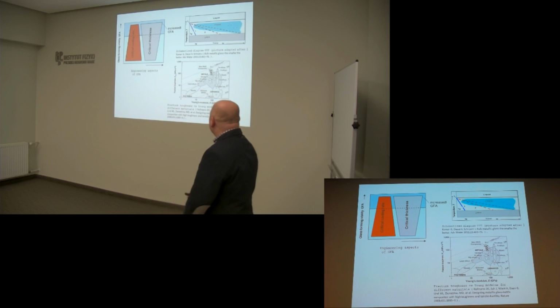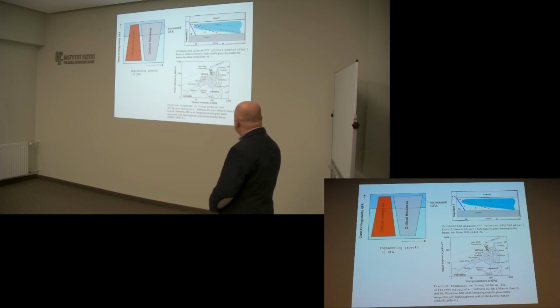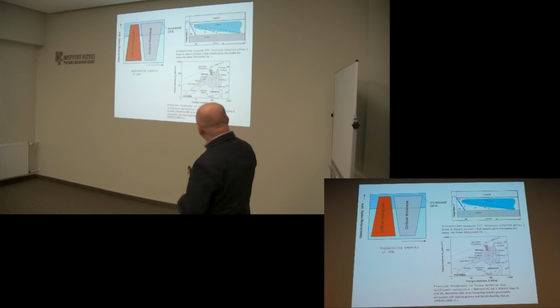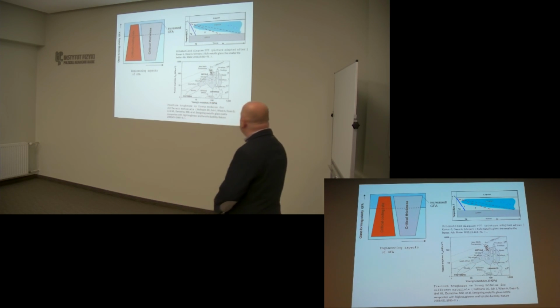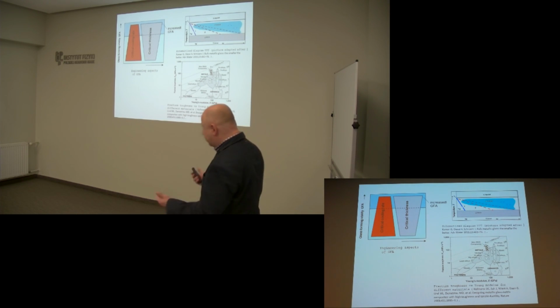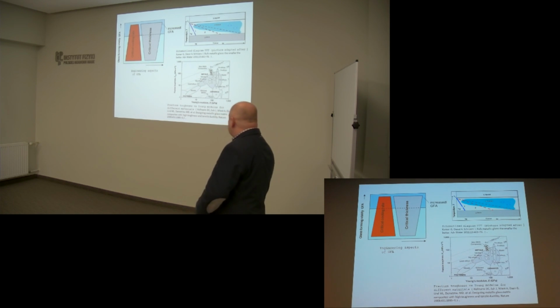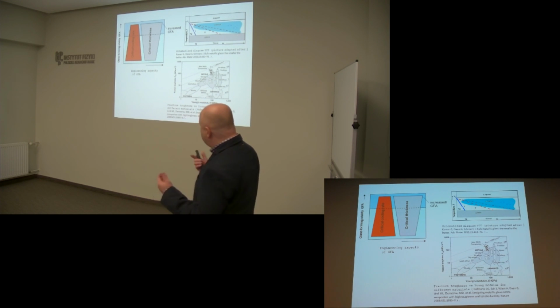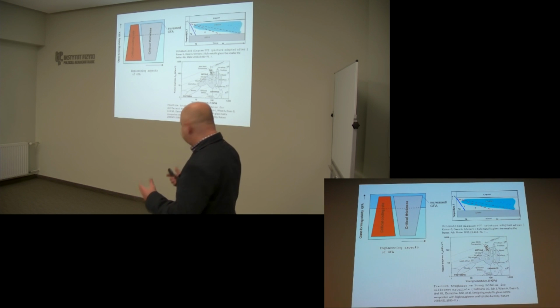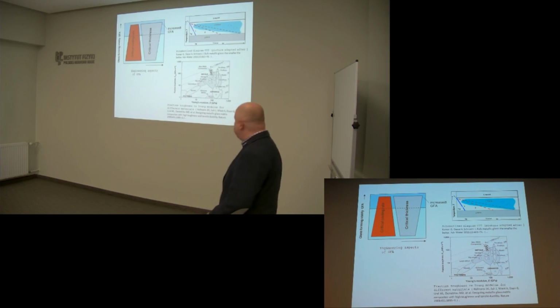Rapid solidification: in order to get a fully amorphous structure, one has to avoid the nose of this time-temperature-transformation curve with a high enough cooling rate. When the cooling rate is not that high and touches the nose of this curve, we end up with a nanocrystalline structure. When it is a very low cooling rate, it will result in crystallization into a microstructure. On the other hand, when talking about alloys, the critical cooling rate for a particular alloy has to be low enough in order to get a large section of amorphous material. There is quite a large number of bulk metallic glasses processed up to now.